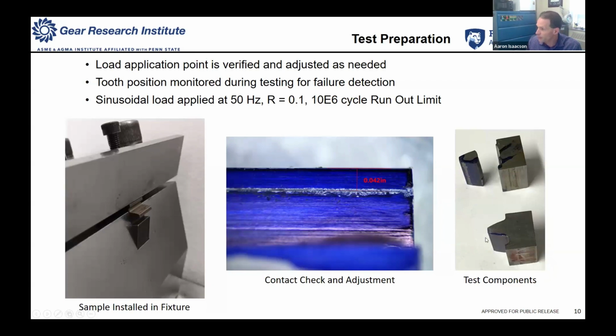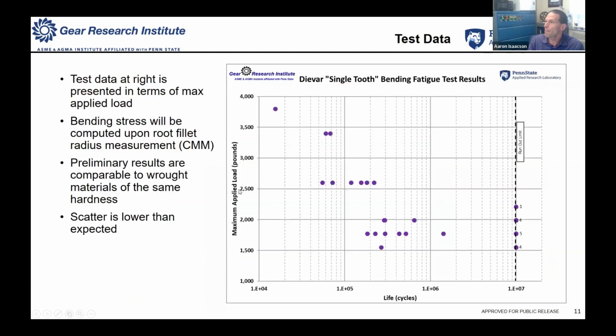Here you can see what a broken sample looks like, with the contact pattern after a full test. That must have been one of the first ones with bluing on. And then this is one that didn't fail, or was a run out, right? So that's what we call a sample that exceeds 10 million cycles without cracking or without failure: a run out. Yeah, I think that's about all I have to say about that.